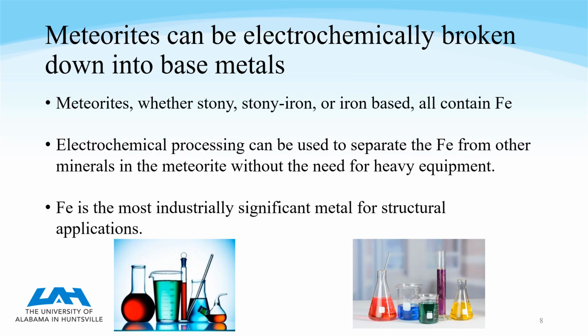Now, meteorites, along with meteoroids floating out in space, and even asteroids, which are just bigger meteoroids, they're full of iron, actually iron and nickel, but here we're focused on iron. We can put that through electrochemical processing, a method called selective electroplating, and we can extract pure iron from these meteorites that we can collect off the surface of the moon or Mars or wherever else. Anywhere that a meteorite has impacted, there are likely to be fragments that we can process and get the iron out of. And the reason we're focused on iron is because it's the most common structural metal that we use today.